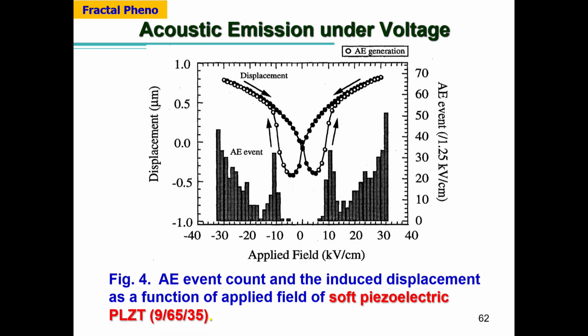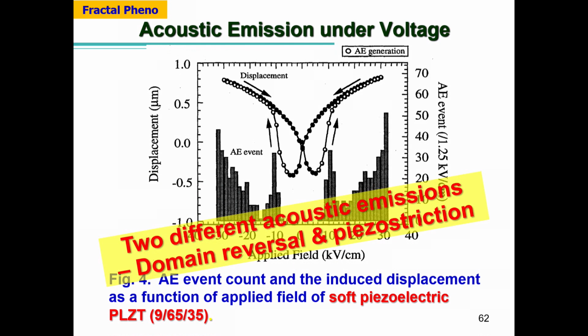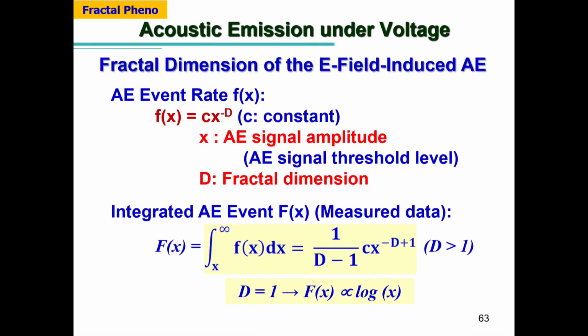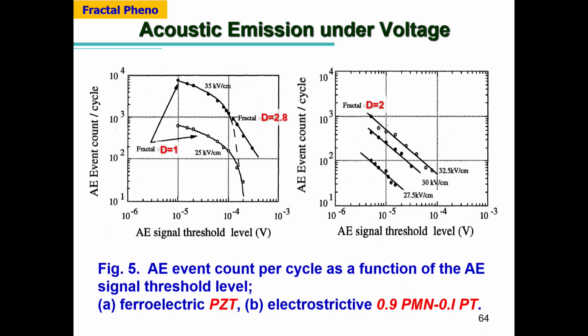And this is rather intriguing, soft PLZT materials. This part is domain reorientation related. One has acoustic emission, another one is already saturated. So this is the piezostriction-like acoustic emission. So we can separate two different acoustic emissions. Domain reversal and piezostriction give different acoustic emission, okay? Again, I don't have time to explain the fractal dimension analytical solution, just believe our theoretical derivation, okay? So the final result: acoustic emission counts versus the acoustic emission signal threshold.